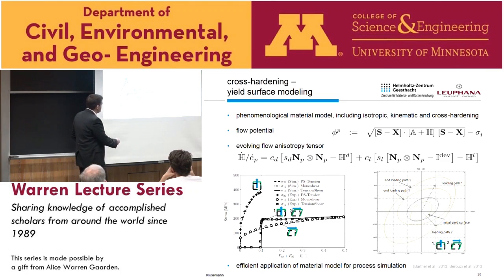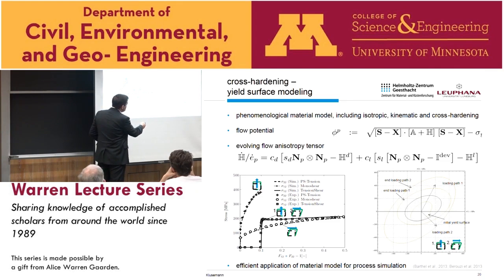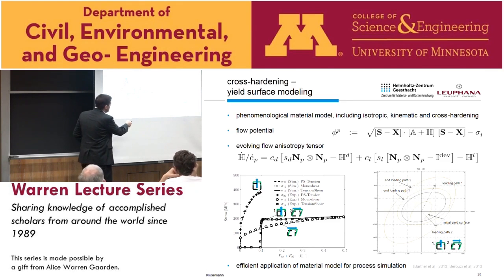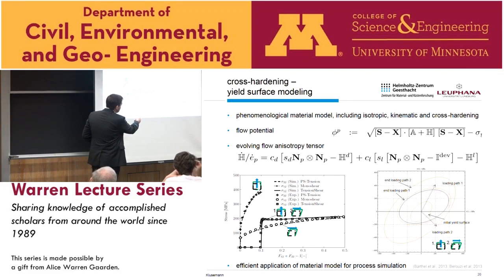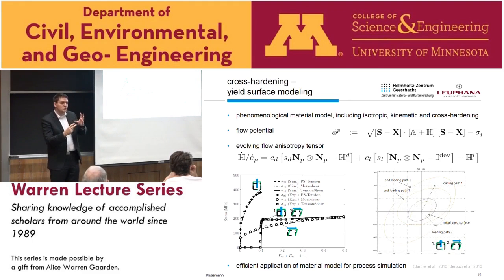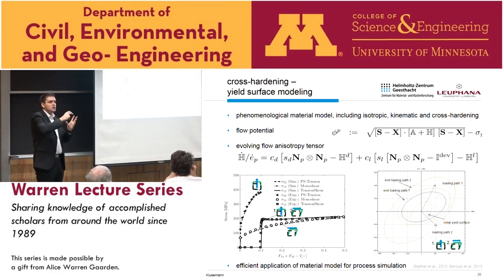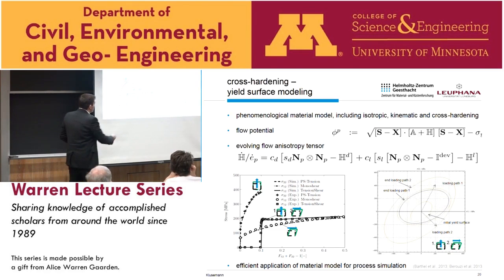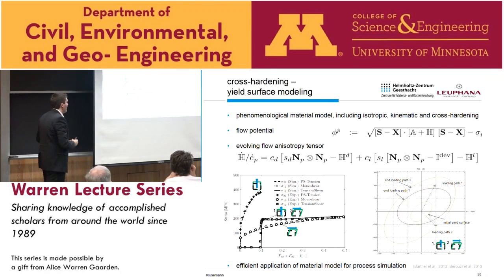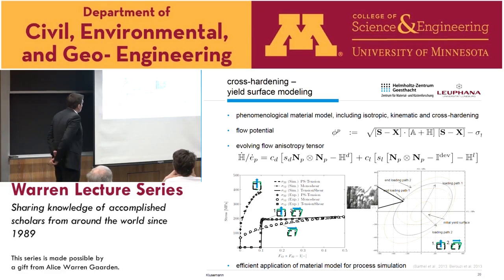And then of course we were able also to investigate our yield surface evolution more closely. Now what you can see here is our classical initial yield surface, so this is for Mises. And then starting from that, we have a loading path which is going in this direction. We're loading in this direction, and this is what our yield surface looks like during this loading path. So we have a change then at this point. We're now loading in this direction from there on. And you see directly a complete shift of our yield surface, which somehow represents this reorganization of our dislocation structure. And by this model, we can now apply this for process simulation.